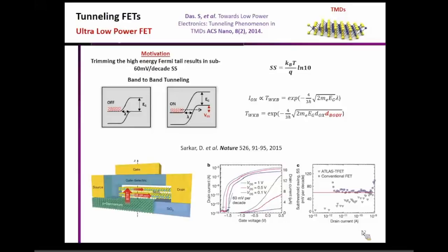But if you look into the tunneling probability, it actually depends on the thickness of the material that you are using for this tunnel FET. And you can immediately see that 2D materials are the perfect choice for this kind of tunnel FET because they offer the thinnest body dimension that you can imagine. That is why, for tunnel FET application, these 2D materials are also very interesting. In fact, there has been a paper from, I think, Kaustav Banerjee's group from UC Santa Barbara, who have demonstrated that in a stack of p-type germanium and MoS2, a vertical tunnel FET achieves slope below 60 millivolt per decade, again cashing in on the advantage of 2D material and its ultra thin body dimension.